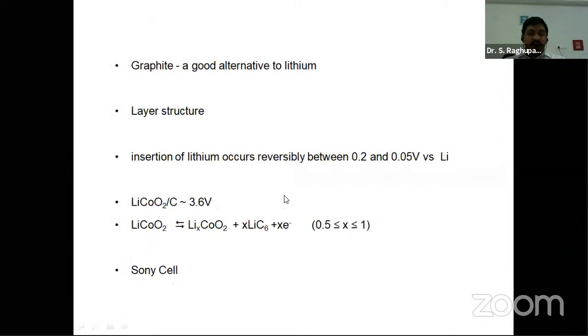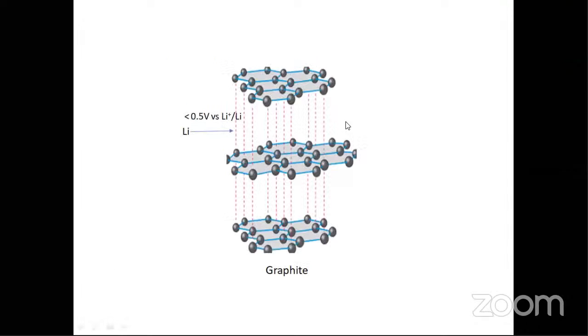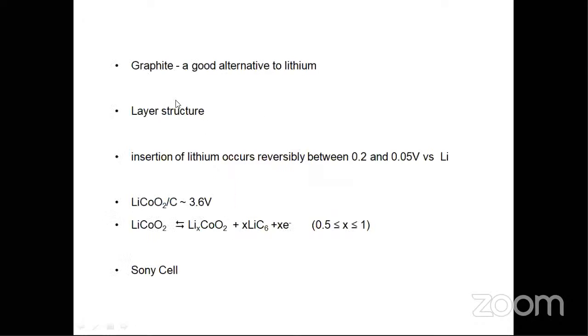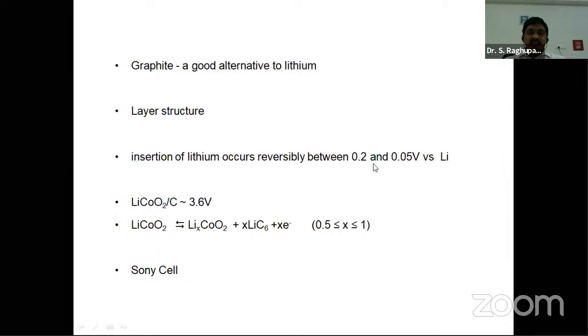So later, as at the beginning of the slides, I have shown graphite. Graphite is at less than 0.5 volt versus lithium, and it has a layered structure. We can easily insert lithium into the graphite and you can take it back. So with 4 volt for LiCoO2 and 0.5 volt for graphite, if you subtract, a battery containing LiCoO2 and carbon or graphite gives almost 3.6 volt. Whenever you buy a new mobile or laptop, you can see the battery voltage written is around 3.6 volts. And here the lithium from LiCoO2 comes out and enters into the graphite.